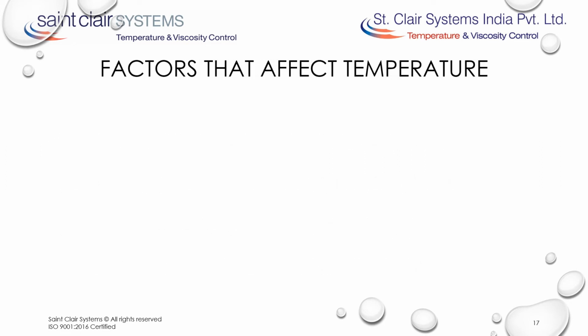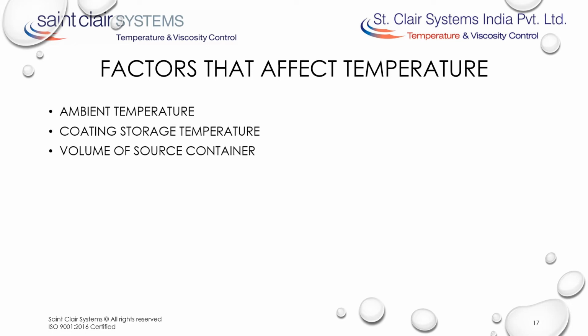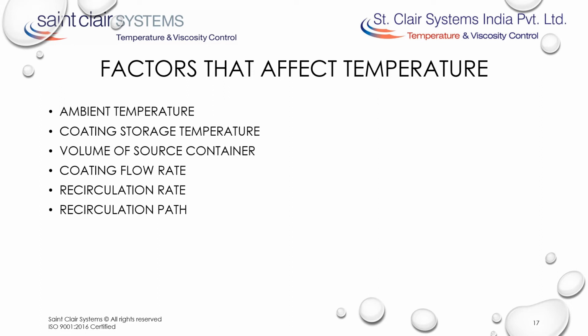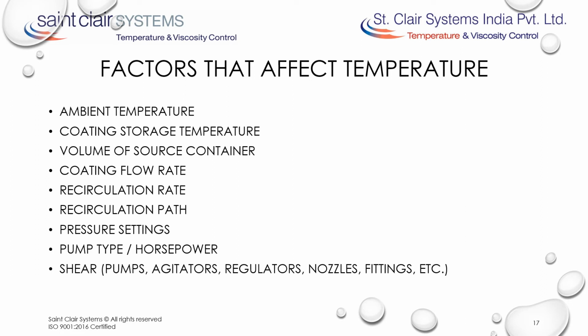So what factors affect temperature? Well, there's ambient temperature, coating storage temperature, the volume of the source container, the coating flow rate, and the recirculation rate and the path through which that recirculation follows, pressure settings, pump type and horsepower, shear, which comes from pumps, agitators, regulators, nozzles, fittings, etc., and the substrate temperature. It's important to remember that friction and shear equal heat. This is the reason that simply controlling ambient temperature is not effective. Besides, it's also important to remember that often the fluid we're dispensing comes into our carefully controlled process from a totally uncontrolled area. This means continuous changes in temperature and therefore viscosity.